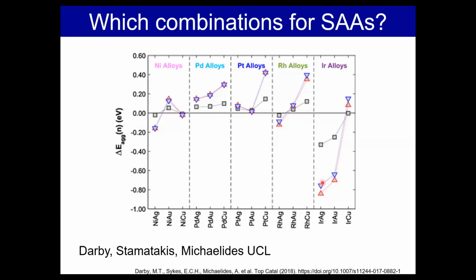Good question, and it's a tough question because of what I just mentioned, is that depending on the partial pressures in the gas phase over the catalyst, that will dictate under steady state what the population of atoms in the surface. So every different reaction will have a different percentage population of those single atoms in the surface versus the bulk. But you can play tricks like you play in regular catalysis. You can make small particles so that you have more surface area per bulk. That's a way to up the active site number. But I would say it depends on the reaction you're trying to run.